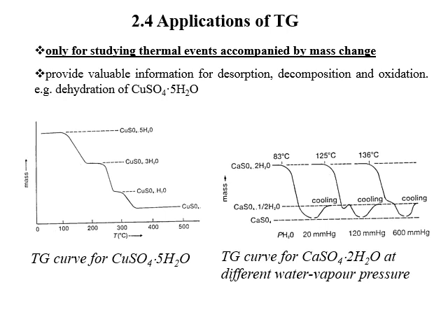We get to about 250 degrees and we see the next step where it loses mass. And then it's relatively stable for a short period of time as the temperature increases. And it becomes copper sulfate with a single water. And then ultimately at about 350 degrees, we lose all of the waters, resulting in copper sulfate.